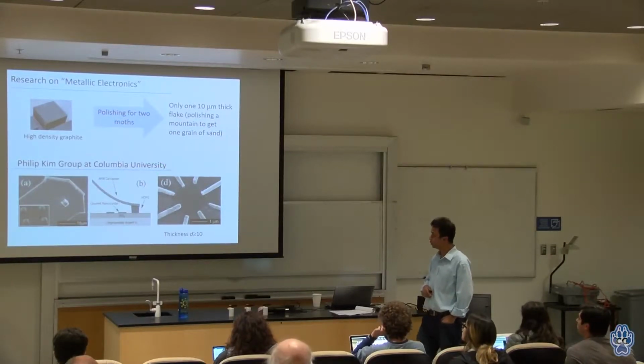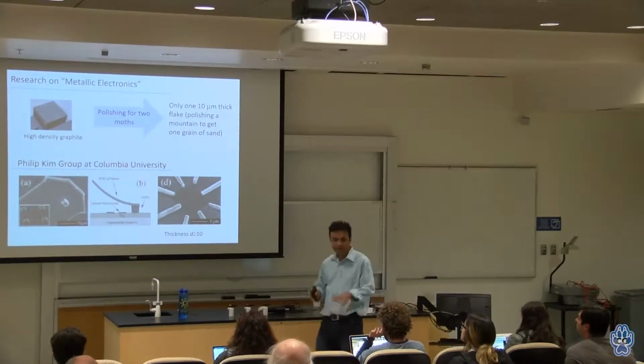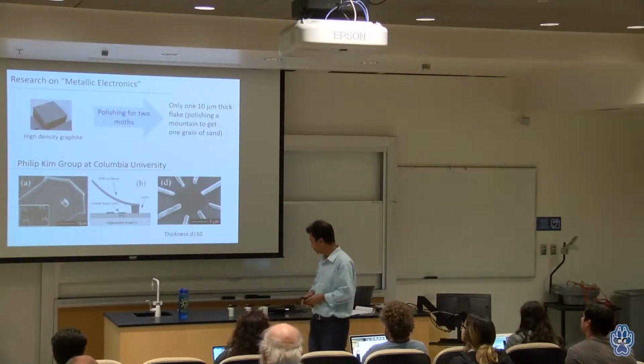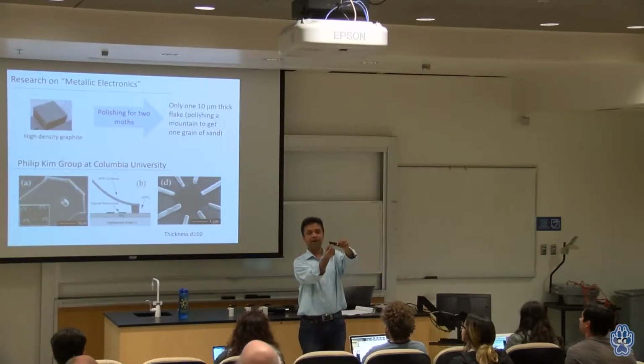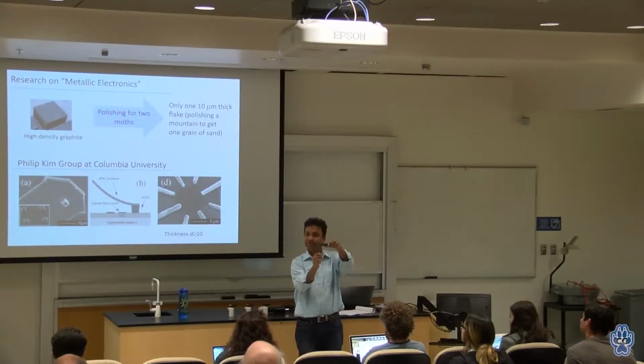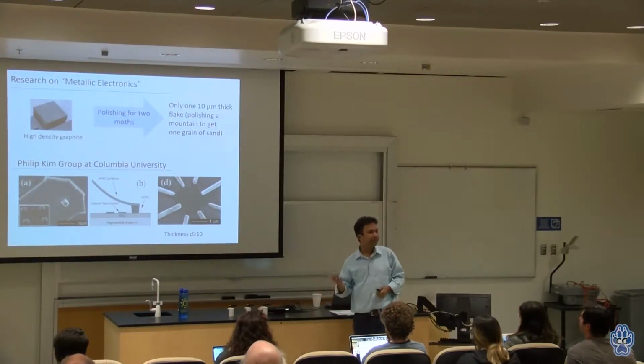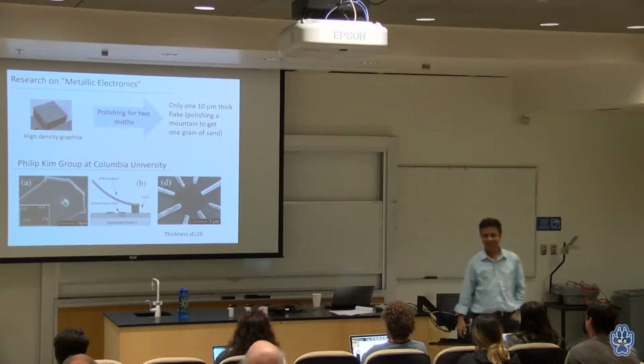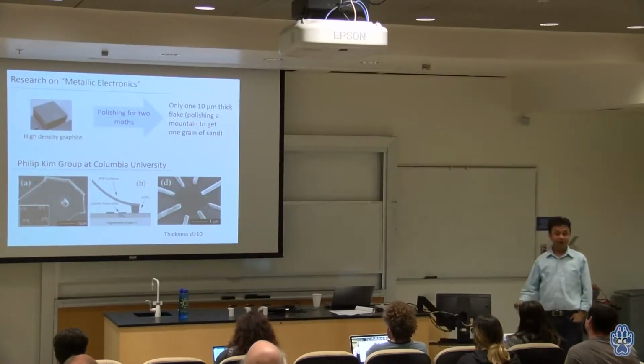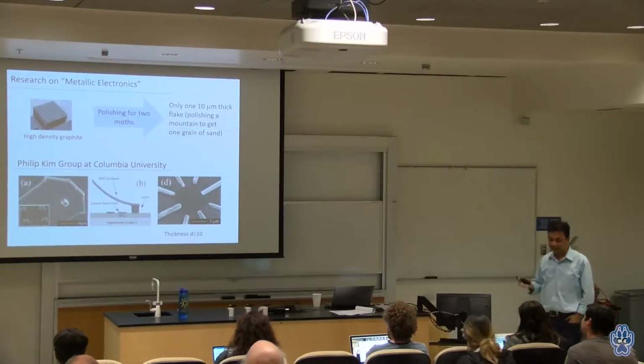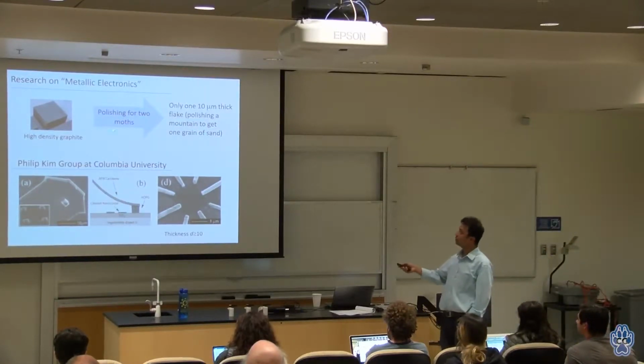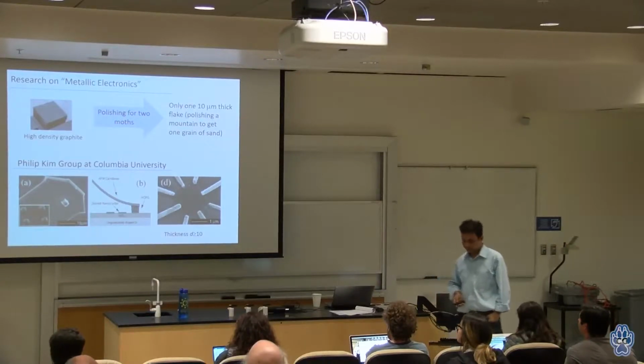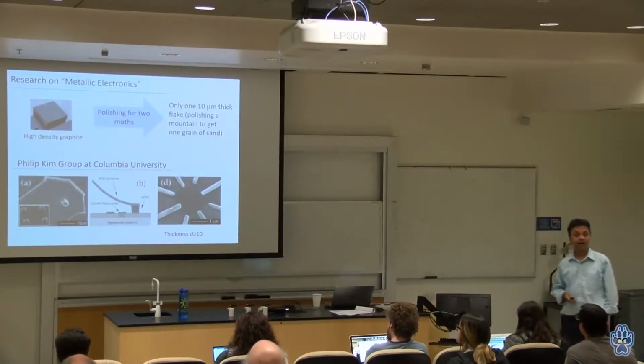There is another group I should mention at the same time. This is Philip Kim's group at Columbia University. They went a more rigorous scientific way. They put a graphite on top of a cantilever tip, made micron size. They call it a nano pencil, and they put it on the substrate and slide it. But even using that, they could not go less than 10 nanometer. But using Scotch tape, I'll show you some of the results, that you can go really to one atom thick materials.